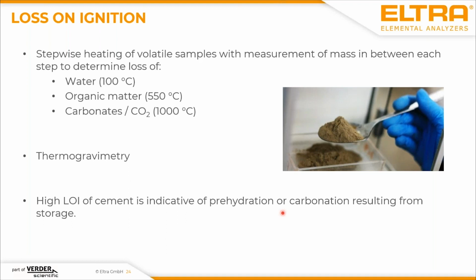And you have different temperatures where different things happen. So of course, first in the range of 100 degrees centigrade, water moisture is coming from the sample. There might be even a second step in the region of 200 to 300 degrees if you have a lot of gypsum, for example, in your sample, where you lose the crystal water. So you have a next step there.